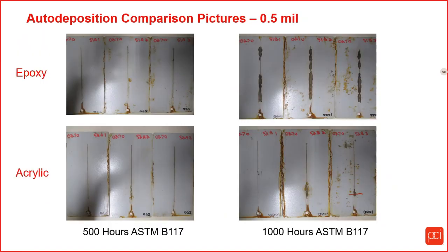Here are the panels. We took 3 panels and then took the average and then graphed them. The epoxy is on the top, the acrylic is on the bottom, 500 hours on the left and 1,000 hours is on the right. You can see for the 500 hour salt spray that there's minimal difference between the 2, so the panels were very similar in performance, where on the right hand side you can see the difference between the epoxy and acrylic performance creep back on the panels.